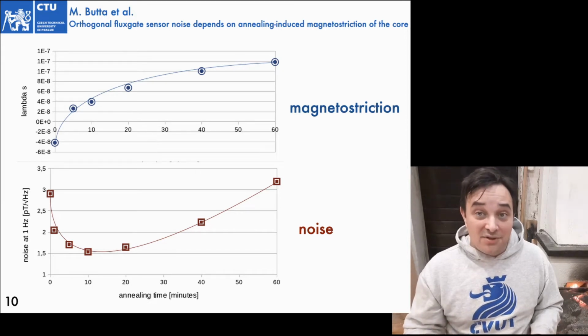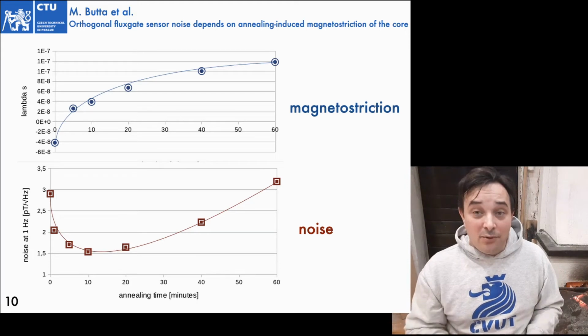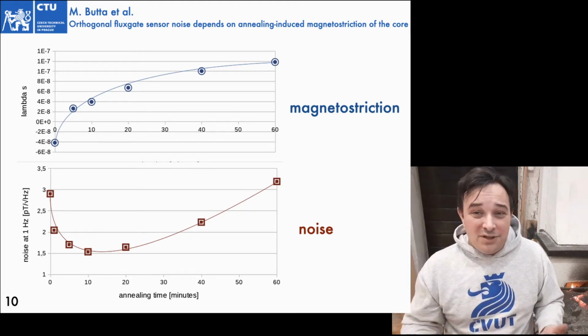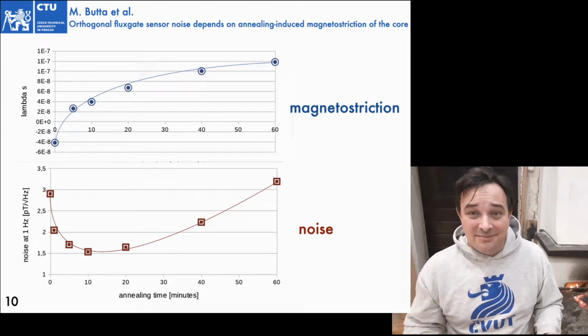But you have a larger coercivity in the circumferential direction. And that means that overall your noise will be lower. Then, if you increase the annealing time, what you achieve is just increasing the magnetostriction, which doesn't bring anything good to your sensor. And that starts to make sense, but we have to verify if this theory is correct.